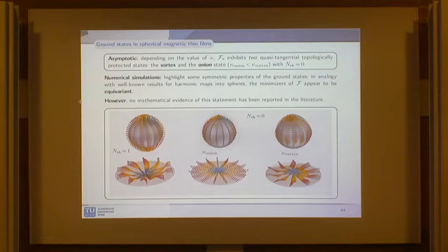That is what happens. So the novelty is that if you have this curl m part, say the normal component of the curl will give you a contribution to that kappa that is written there. So it will not be kappa, it will be kappa plus something. It modifies that term. And then the other part of the curl will give you just the tangential curl, tangential curl dot m, the magnetization. But I did not investigate which are the minimizers in this case, when you also have the curl m dot m.